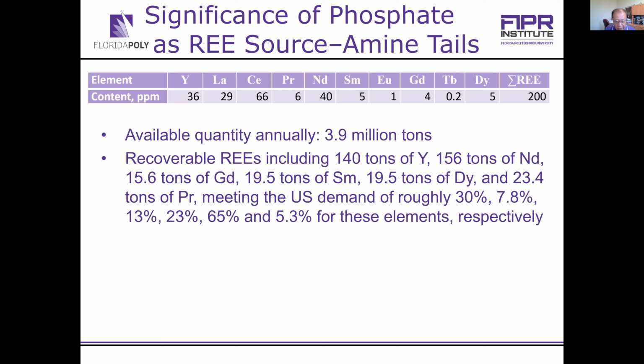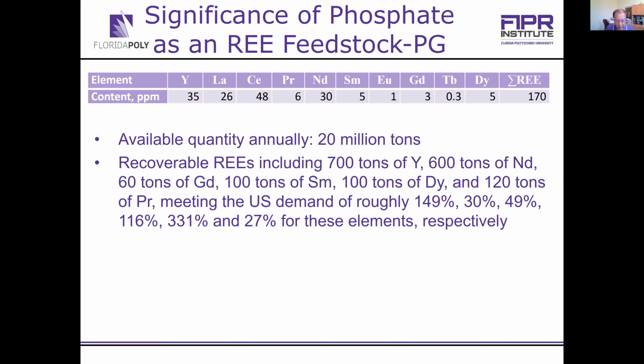So based on this 3.9 million tons per year amine flotation tailings, again, we can produce a significant amount of critical rare earth elements, meeting a significant portion of the U.S. demand for this element. Phosphogypsum, again, annual production roughly 20 million tons, which also represents much of the U.S. demand for this rare earth element, particularly yttrium, neodymium, scandium.